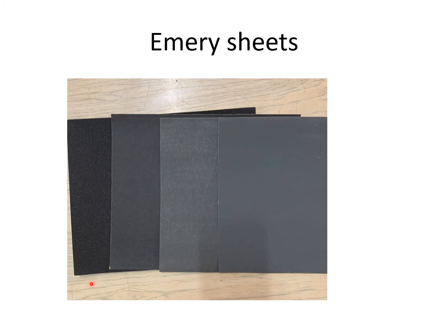You have to keep it at 90° to the scratches made by the belt grinder. You create new scratches from this emery sheet, and these new scratches will be removed by the 400 emery sheet, then those scratches by the 600 emery sheet. The 600 emery grade scratches will be removed by 800.